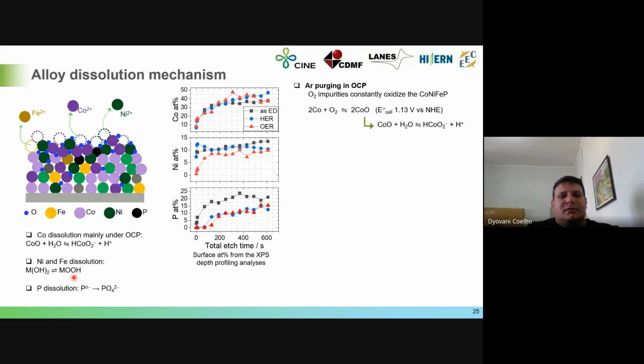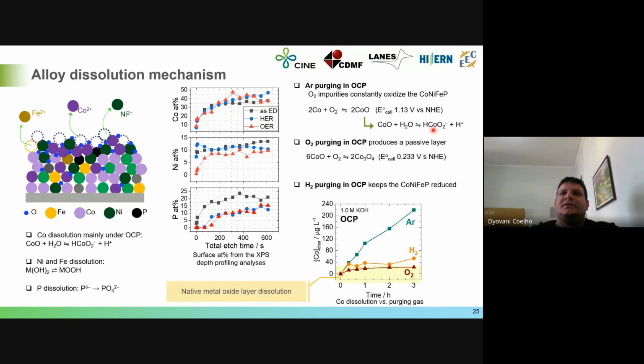So that is why, in the catalyst for the oxygen evolution reaction, we can see nickel dissolution. There is no nickel on the surface, but for the electrodeposited catalyst and for the hydrogen evolution reaction, we can actually see nickel. Phosphorus is not stable at all. So when we put the catalyst in the electrolyte, the phosphorus on the surface is just dissolved. With argon purging in open circuit potential, what actually promotes the catalyst dissolution is the impurity of oxygen inside the gas. This impurity of oxygen produces the cobalt oxide, and the cobalt oxide is again dissolved by the production of cobaltite.